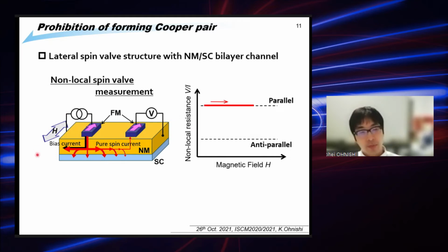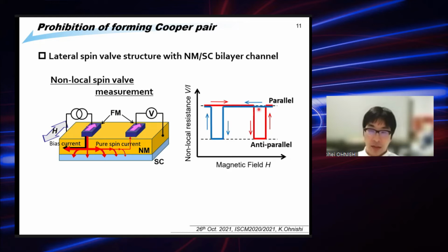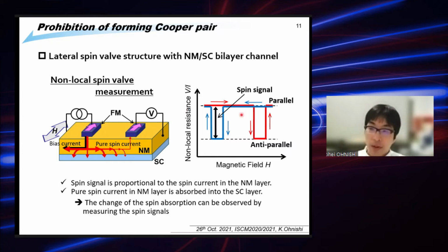So when I sweep the magnetic field, at some field one of them is flipped, switching to the anti-parallel state. Anti-parallel state means the low resistance state. Then by applying more magnetic field, the other magnetization at the injector or detector flips, and they recover to the parallel state. In the negative field, we can observe the same feature. So by performing the non-local measurement, we can obtain the magnetic field dependence of non-local resistance like this. The point is the spin signal.